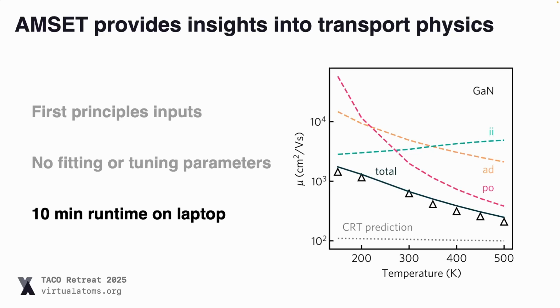And what's nice is that you do actually get kind of insight into the scattering physics of the material. So you can see that there's a crossover between ionized impurity scattering at low temperatures and polar optical phonon scattering at high temperatures. And when we compare this to the kind of result predicted from these constant relaxation time methods, which are also quite popular, you can see that that doesn't get the temperature dependence or the magnitude of the mobility right at all.